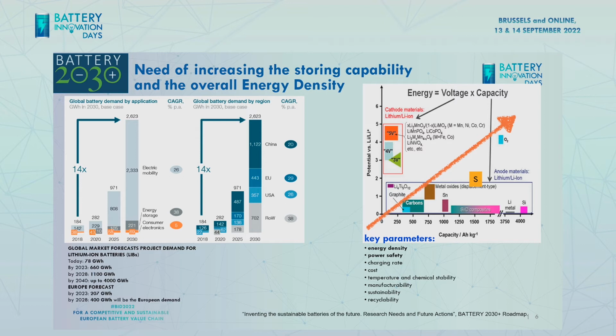And how can we achieve this higher energy storage? We have two ways: we can work both on voltage and on capacity, and this is more or less what everybody is doing in the choices they make in combining anodes with cathodes. Commonly, cathodes are the ones working at higher voltage, so most people are pushing the voltage higher and higher, making the system somehow less stable, because it is more and more difficult to find the right electrolyte that works properly at very high voltage. But still, this is needed in order to increase the overall specific energy.